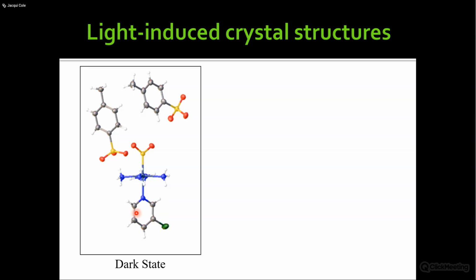In this case, this is 3-chloropyridine, again, trans to the sulfur dioxide group, and this is all in an asymmetric unit. This is Y. Remember, there are counter ions, so this is the tosylate. There are 2 tosylate groups, and of course they're not doing much photo action, but actually they're important because everything's happening in the single crystal. So all of this is very much constrained in what they call a reaction cavity, because, of course, there's only so much volume around here, and depending on the counter ions, they can actually be quite important for more steric reasons. So this is an asymmetric unit of the 3-chloropyridine example where we're changing X.